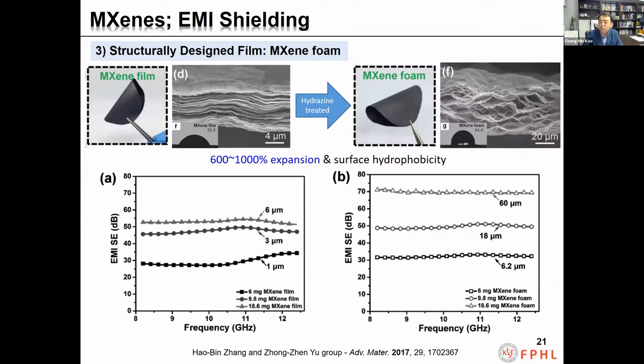In 2017, Professor Hao-Bin Zhang and Zhong-Zhen Yu from BUCT in China published one interesting paper on MXene porous foam. They fabricated MXene foam by using hydrazine treatment. After treatment, the compact MXene film expanded more than 600%, forming a porous foam structure like this. The expanded foam structure enhances internal scattering effect and improves the shielding effectiveness from 50 decibel to 70 decibel for 6 micrometer thick MXene film. This paper stimulated investigation of the structural design effect of MXene materials.